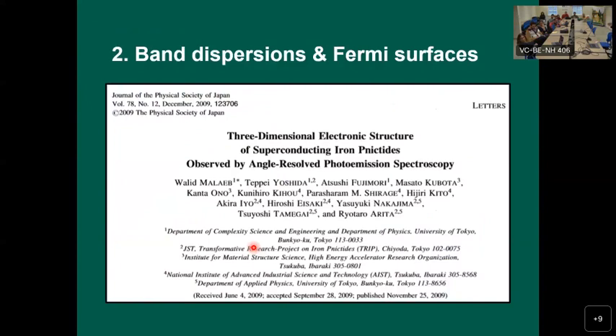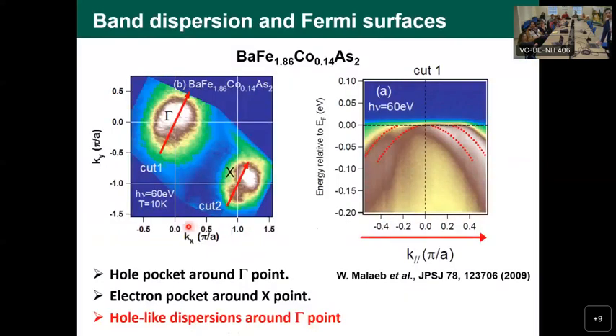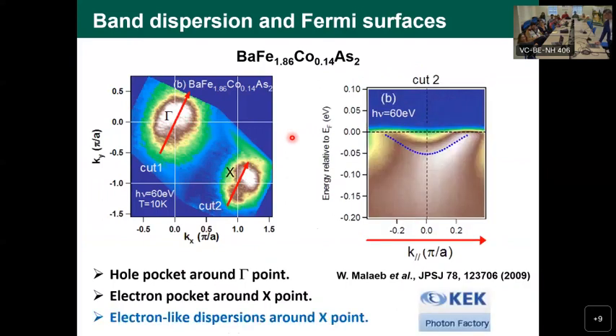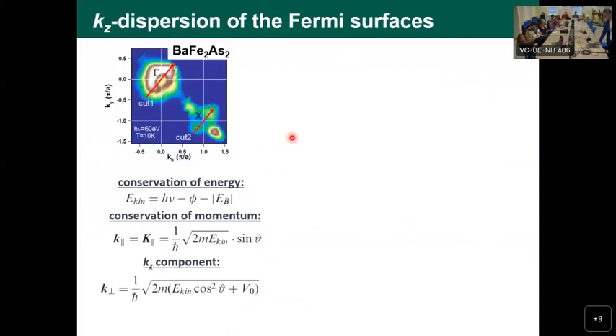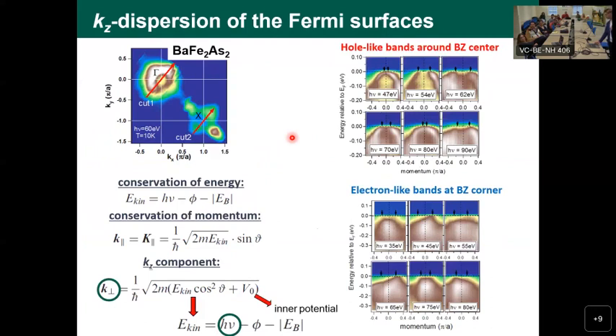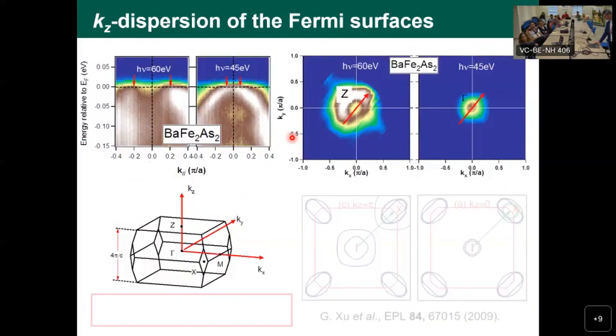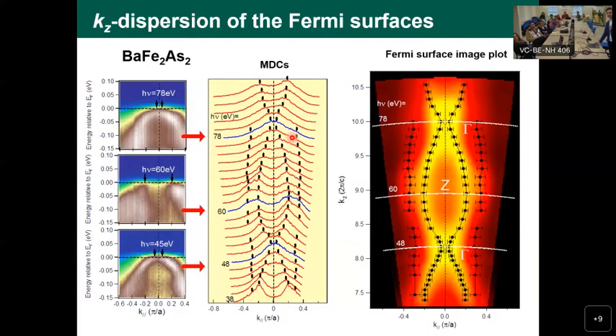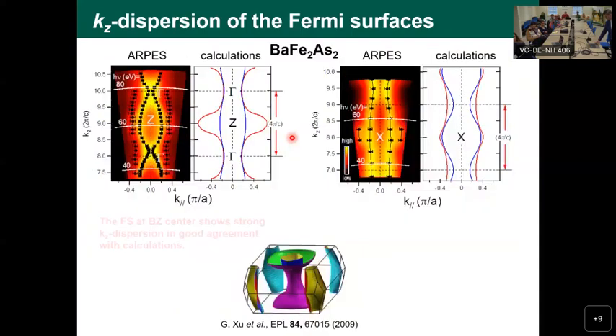A few months after that, the single crystals became available, and we did a more detailed study, which is the ARPES, angle-resolved study, for this compound. And here we presented the Fermi surfaces near the Brillouin zone center with hole-like bands, near the Brillouin zone corner with electron-like bands, and so on. And using the advantage of the synchrotron radiation, we varied the photon energy. This allowed us to probe what we call the kz direction. So we checked the photon energy dependence. I'll skip the details. I'll just show you that we had a strong kz dependence, which means that the Fermi surfaces along the kz direction vary a lot. So this was a new property revealed by a high-Tc superconductor. We know from cuprates that only two-dimensional materials host high-Tc superconductivity. So this was very new regarding these materials. This is a summary of that work.